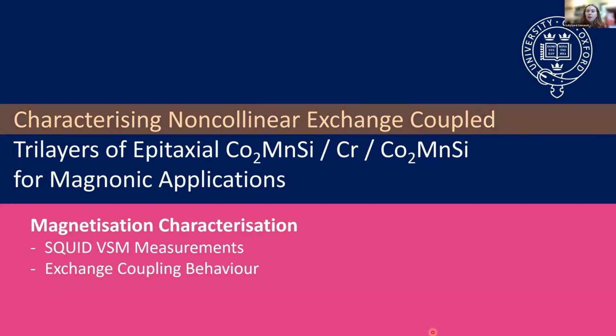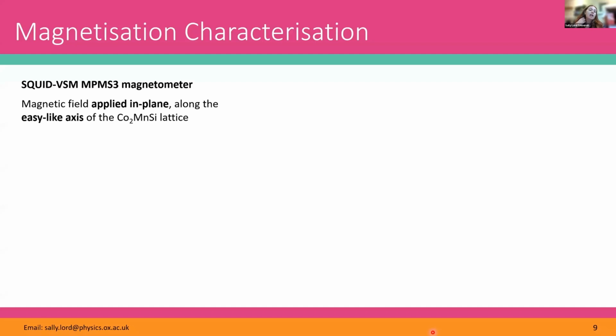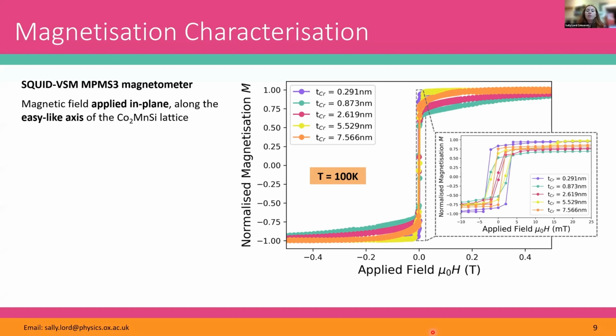So after we'd fabricated the samples, we then wanted to characterize the static magnetization properties of the samples in order to extract some information about the exchange coupling between the two ferromagnetic layers. The magnetization characterization was carried out using a SQUID VSM magnetometer. And for all the measurements, the magnetic field was applied in plane along the easy axis of the cobalt manganese silicon lattice. And here on the right in this figure, you can see the magnetization loops for a selection of the samples for various different chromium interlayer thicknesses.